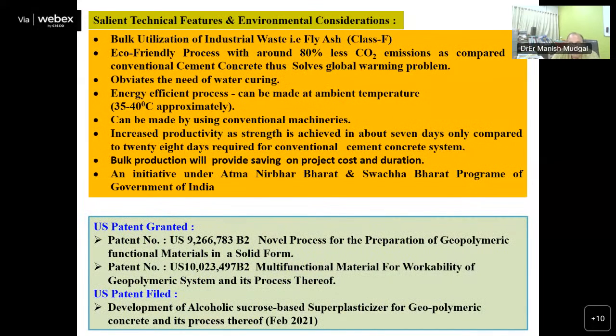So with the development, the salient technical features are: bulk utilization of industrial waste, that is class F fly ash; an eco-friendly process with around 80% less carbon dioxide emission; it obviates the need for water curing; an energy efficient process, only at 35 to 40 degrees centigrade; and it can be made using conventional machinery. Increased productivity, and strength achieved in 7 days only, as compared to 28 days required for conventional cement concrete. Cement concrete needs 28 days for development of around 90% strength, whereas in this system we can develop it in 7 days only.